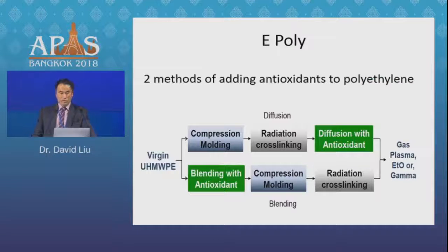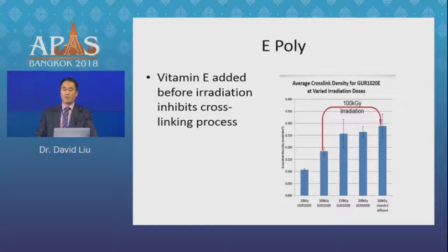And there are two processes of how you add the vitamin E. You can either add it by diffusion, which means after the cross-linking process, or you can blend the vitamin E with the polyethylene prior to the radiation cross-linking. I happen to use the Biomet E-Poly just because that's what was available to me from the start, and I guess as a result of that I'm somewhat Biomet brainwashed, and so I use the diffusion type, which is what they have.